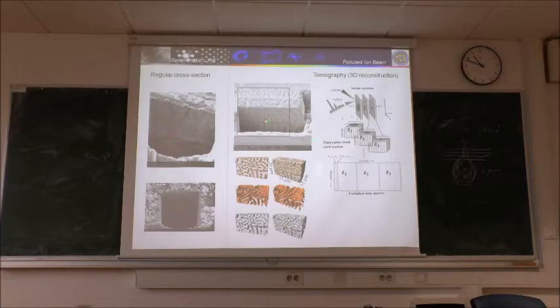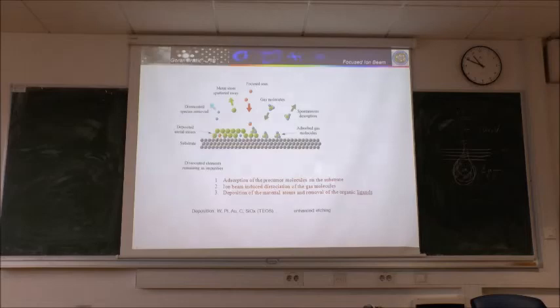Not just imaging, we can also do some tomography or 3D reconstruction. We can cut a layer, like here. We can identify it as a signal, as an image, or even using X-rays, we can determine the chemical composition. Then we slice away another slice and another slice. We get so-called data cubes from every such slice, and at the end we can reconstruct the three-dimensional real sample here, like the distribution of, I think it was copper and iron or aluminum, something like that. This is one example.